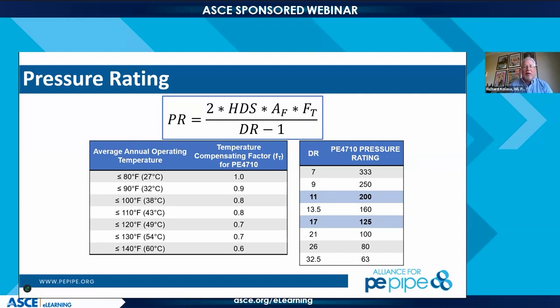Establishing your pressure rating. One of the important aspects of establishing the pressure rating is really there's two factors. We evaluate polyethylenes at 73 degrees Fahrenheit, or 23 degrees Celsius, or ambient temperature. But as we warm the pipe, of course, it's a thermoplastic, it'll absorb that heat. We can soften it. So if you have an application that you need to test at a higher temperature, then what we will do is derate that product based on these temperature compensating factors, which we have per degree Fahrenheit. So we can do that.